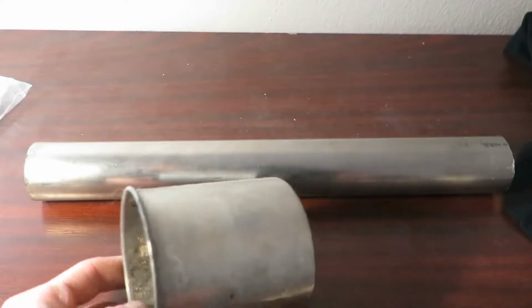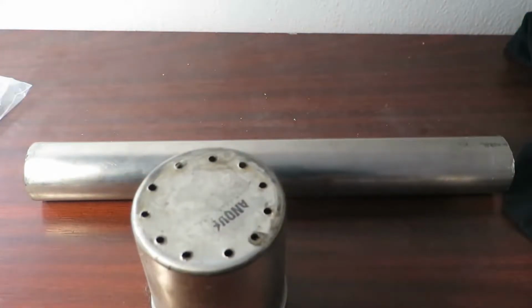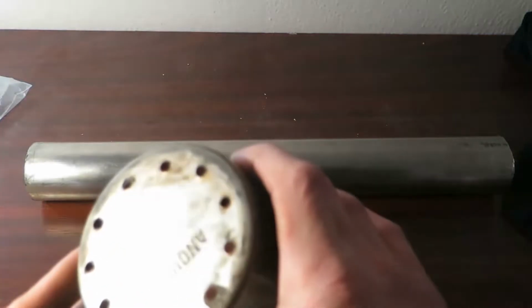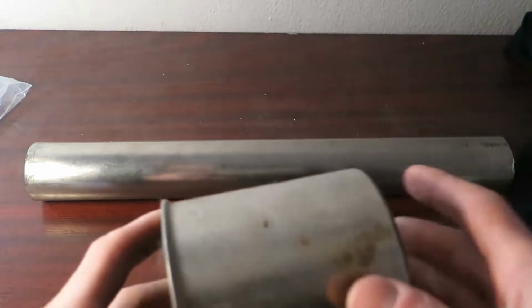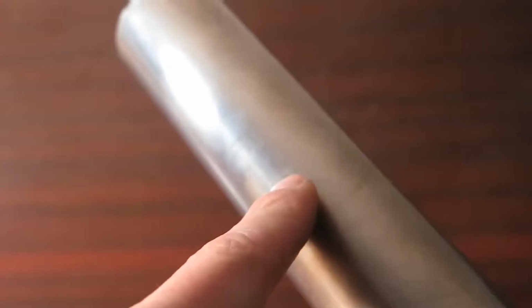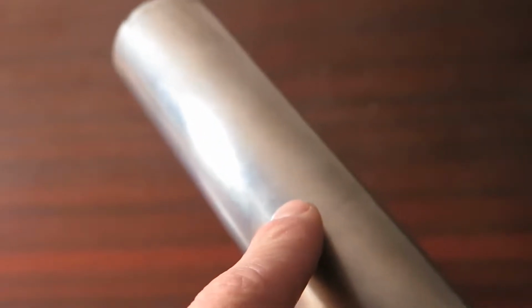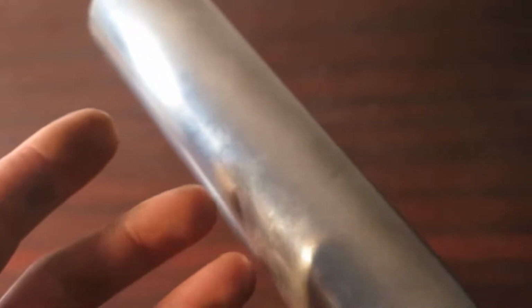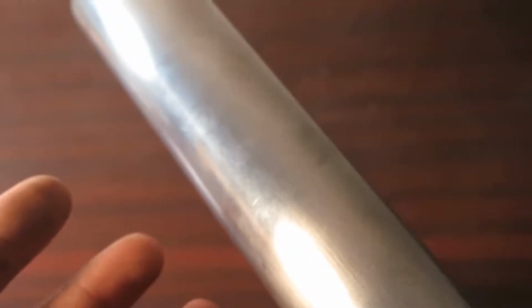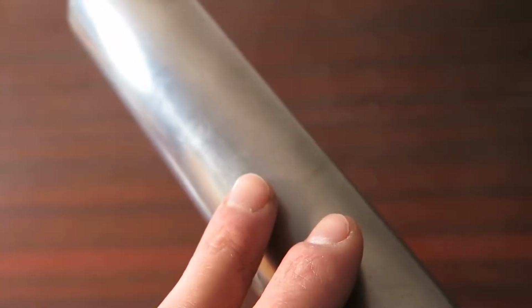For example, this kit of kitchenware, it's stainless steel, at least it says so. And what you can do is put salty water there and in a few weeks it's a mess. So in my eyes the corrosion resistance of stainless steel to chlorine ions seemed to be very low. So at this point I was quite curious what the chromium and nickel content of this steel is. I was expecting something around, I don't know, 60%. In reality it's about 20% of chromium there, and that's all. Yeah, and maybe about 2% of copper for some reason.